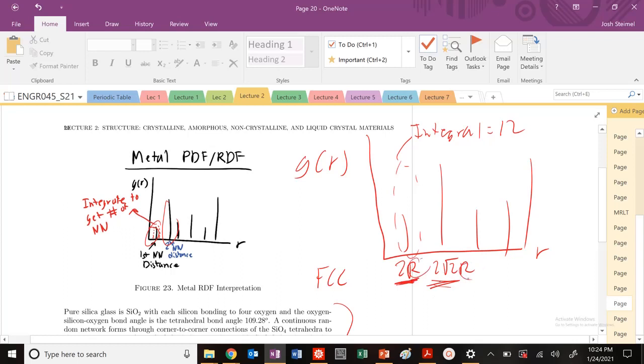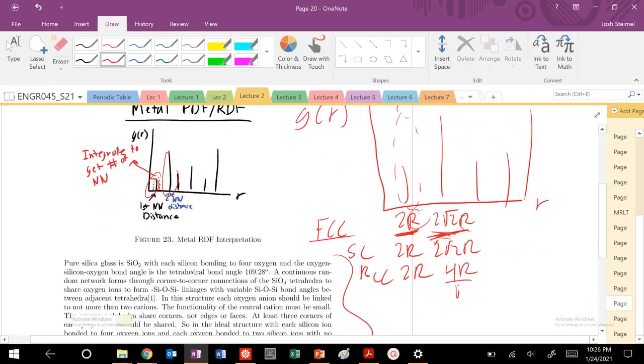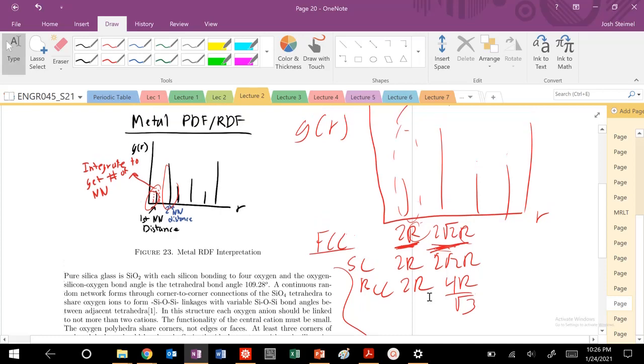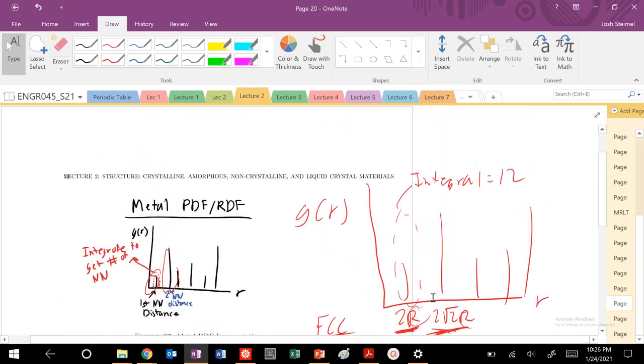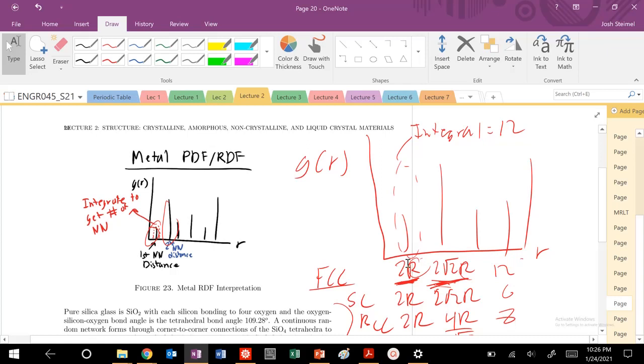Alternatively, if you're given this, that this spacing was 2R and 2√2R, I know that it's either FCC, and the one thing you want to be careful of is, simple cubic also has this structure. If this was BCC, this would also be, so this is for simple cubic 2R, 2R. BCC is 2R, and then this is also, for BCC, it is going to be 4R over √3. So, and again, for FCC, the integral of that first peak is going to be 12, the integral of that first peak for simple cubic is going to be 6, and BCC is 8.